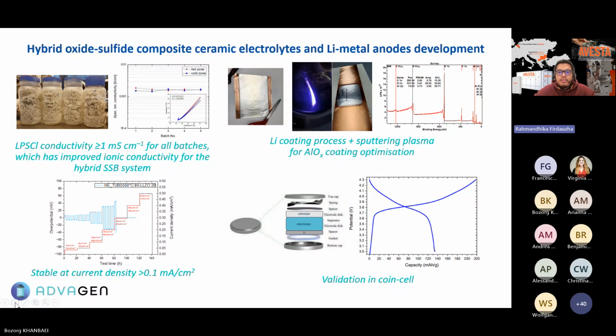And we also developed the protective layer on the lithium metal. Besides, we produce the lithium metal on copper by using thermal evaporation. We also tried sputtering plasma for aluminum oxide coating optimization, and it was also successfully done. Once we combine the LPSCL and the lithium metal anode, we have stable performance at a current density of more than 0.1 milliamp per centimeter square.